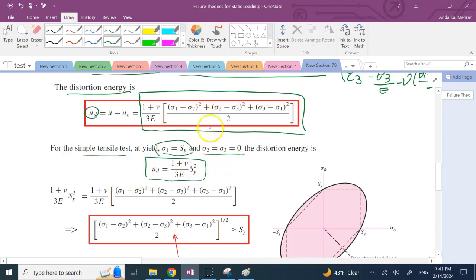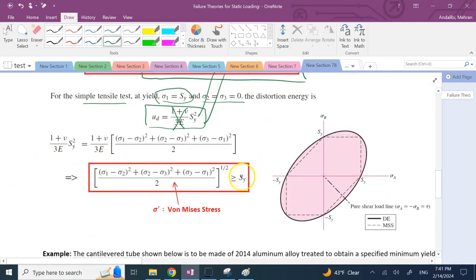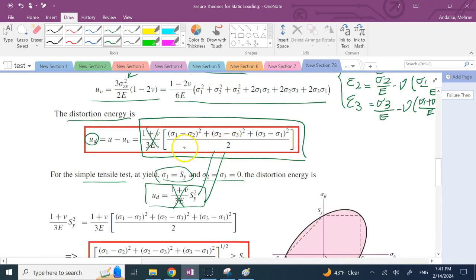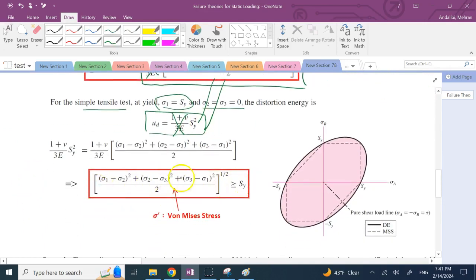Okay, and now if we say these two strain distortion strain energies are equal, then this constant term in both of them can be eliminated, and you get what? You get this formula down here. You take a square root from both sides, and you get this formula, which says as long as this square root, which is sigma 1 minus 2 squared plus 2 minus 3 squared plus 3 minus 1 squared, the whole thing divided by 2, is bigger than or equal to Sy, that means what? Failure. And if it's less than Sy, then it means no failure, or safe.